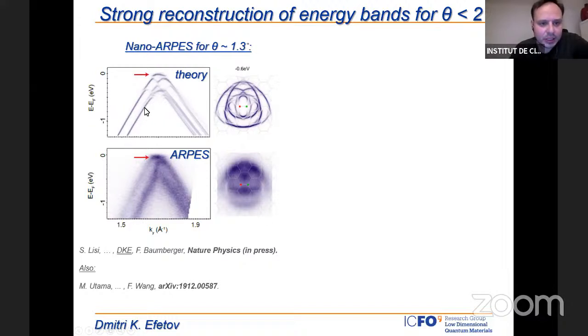But what happens now is that instead of those two bands running smoothly across the energy spectrum, we actually see strong renormalizations happening, and these renormalizations lead to band gaps appearing in the spectrum, and for certain twist angles very close to 1.1, we also see that some flat band regions, which are very isolated from the rest, can appear.